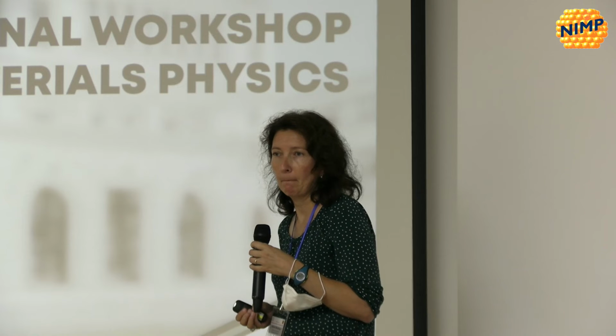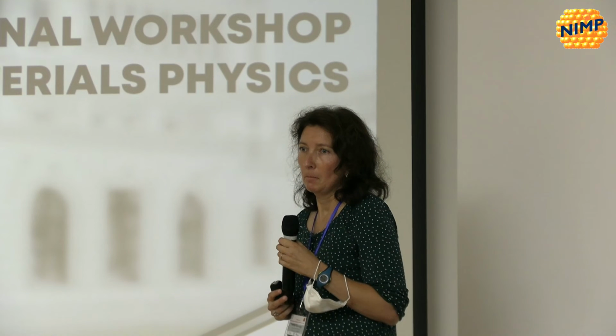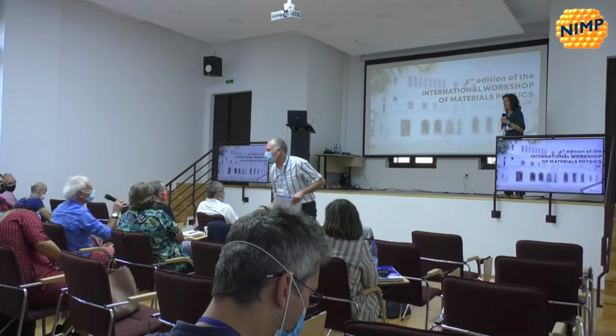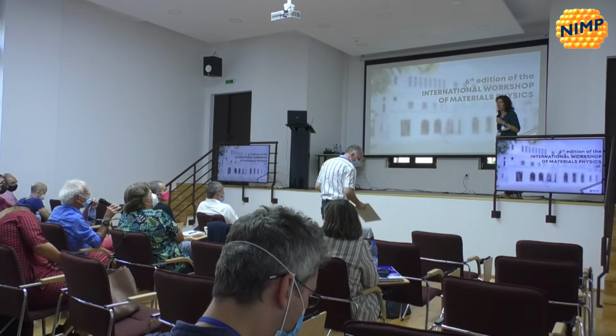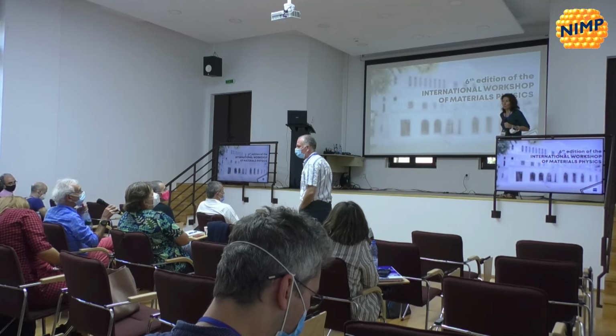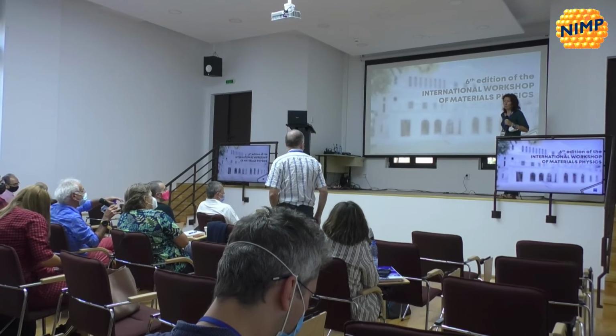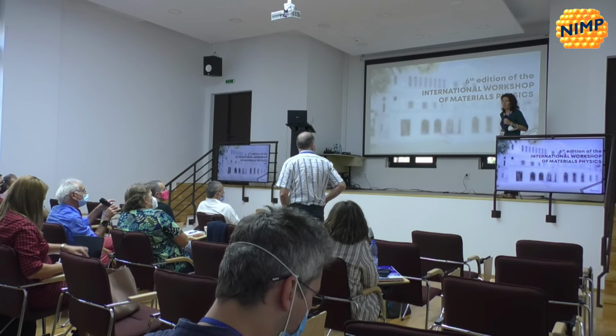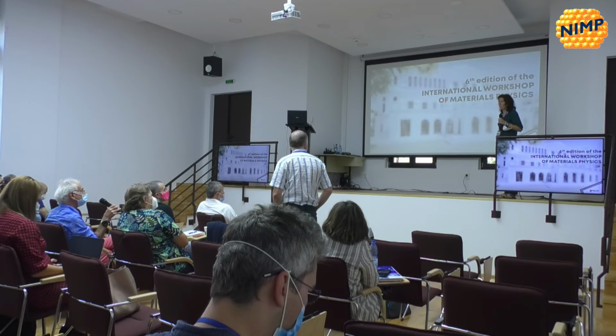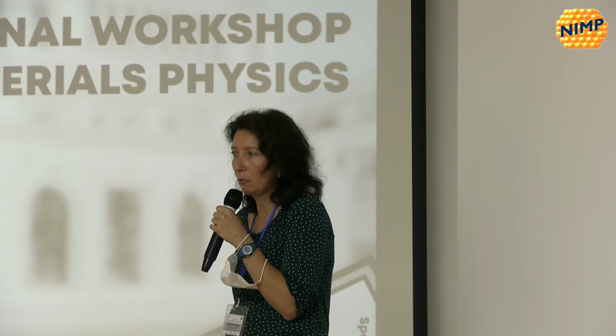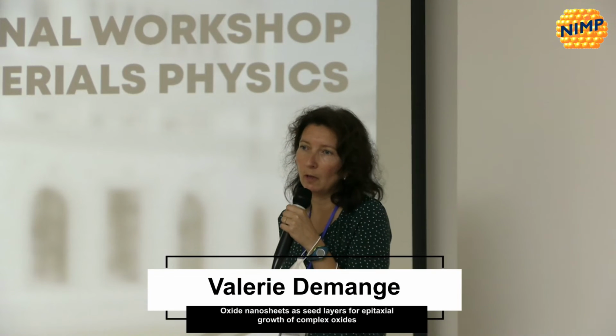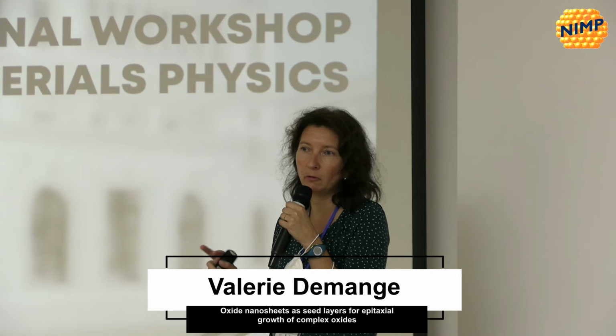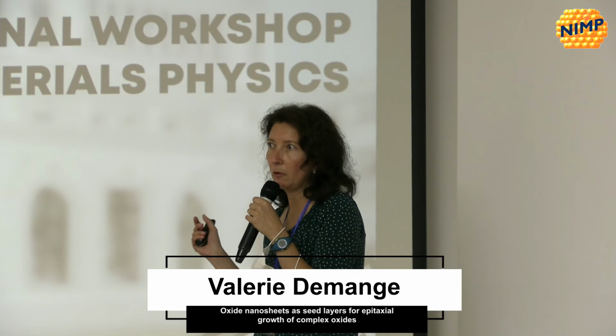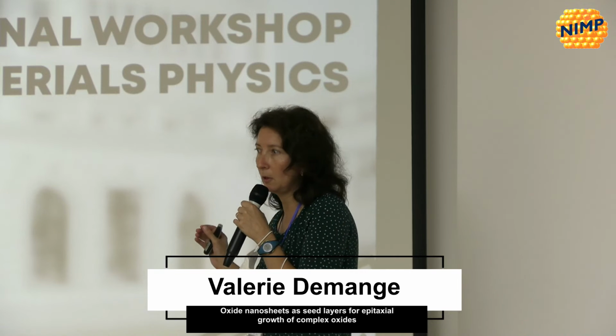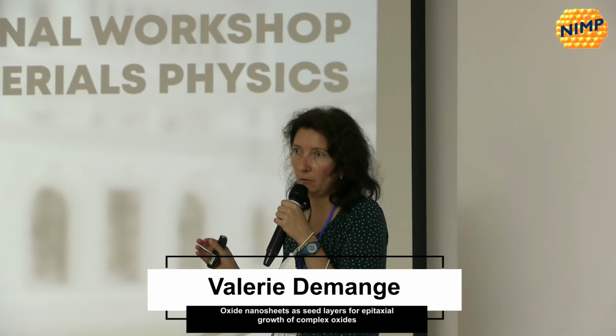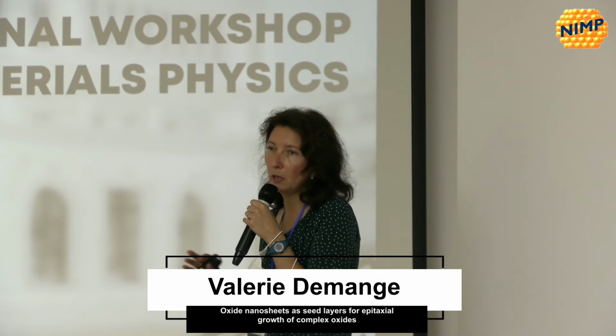Other questions? Which is the lateral size of these nanosheets? Maybe I missed the point. When you prepare the nanosheet and then you deposit it on top of a silicon or whatever surface, what is the lateral size of these nanosheets? Most of our work was made with nanosheets sizing between 2 micrometers and 15 micrometers, something like that. We have larger nanosheets, but for the moment we didn't have results because it fails. So on average it's 10 micrometers.